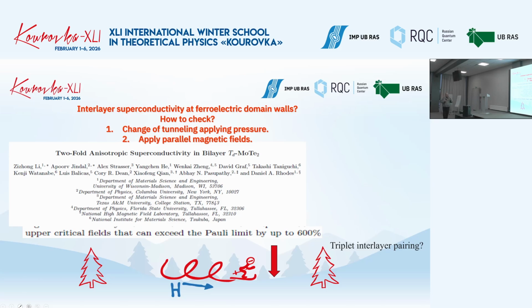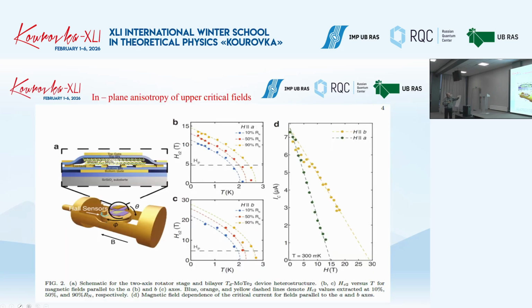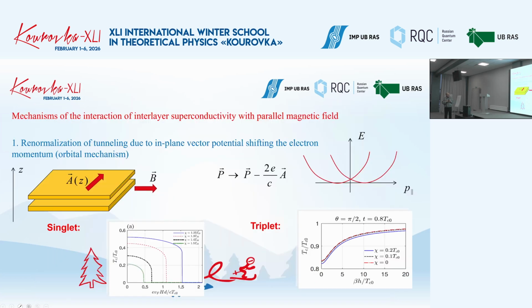Another interesting experimental thing is that they observed twofold anisotropy of the critical field in the plane of the layers. I have some pictures, you can see here, and look at these figures. It's the critical field as a function of temperature. If we apply the field, say these are layers, in this direction or the perpendicular direction, they are different. It's twofold anisotropy. And this also requires some sort of explanation if we want to consider this interlayer superconductivity scenario.